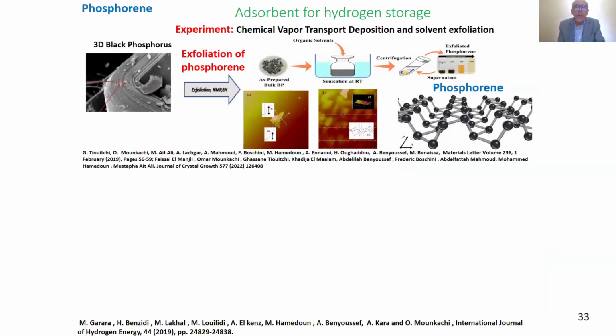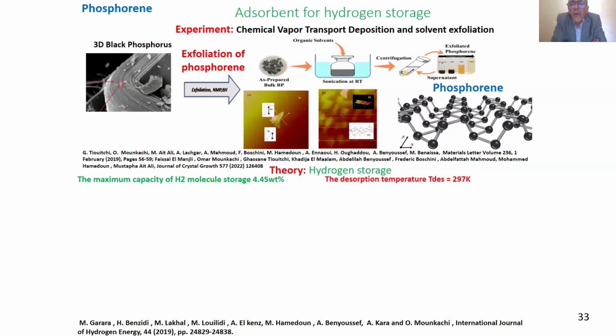I will end with this example. I go back to phosphorene. As I said before, it is obtained from layered black phosphorus using exfoliation in a solvent with sonication and centrifugation. And this material can be used for hydrogen storage. It gives a very good value for the desorption temperature, which is around room temperature, and the gravimetry is more than 4 weight %, and it can be improved by some modification.